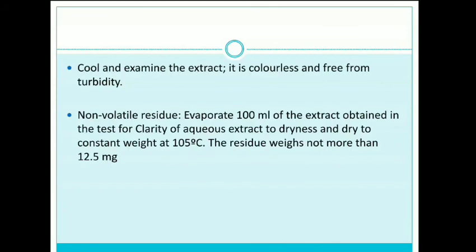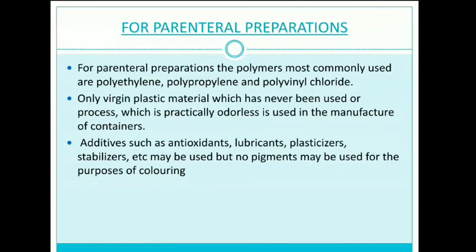The next test for the plastic container for non-parenteral preparation is non-volatile residue. Evaporate 100 ml of the extract obtained in the test for clarity of aqueous extract to dryness and dry to constant weight at 105 degrees Celsius. The residue weight should be not more than 12.5 mg. So these all are for the non-parenteral preparation.